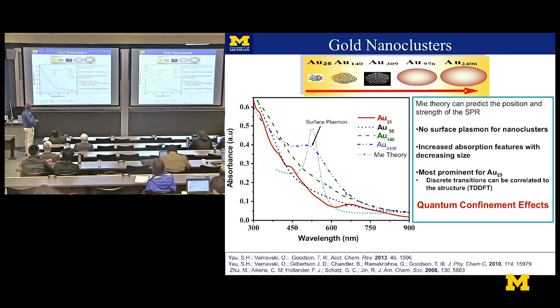And you can see, for the big particles, this is what you expect. This is called a surface plasmon absorption. This is the absorption spectrum. This is called the surface plasmon. As you make this bigger particle down to about 2,000 atoms, you can see the plasmon is more broad but spread out. By making the first known stable magic number, 140, the surface plasmon vanishes. But it's still a particle.